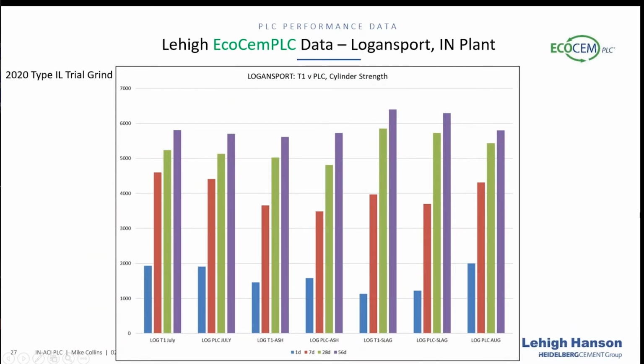If we look at strength data, and again, this is kind of busy, so what I want to do is hide some of this. On the very far left is our Logansport Type 1 sample from July, just our regular sample that we get each month out of that plant. Then we did our PLC trial grind in July as well. We put those two powders in the same mix design, same aggregates, same chemicals. We used a mid-range water reducer, 3 ounces per 100 weight dose, and this is what we got. And then we said, okay, that's really pretty close.